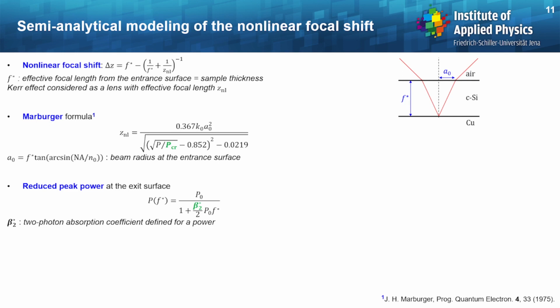And we also modified this formula because for silicon, you have to take into account the losses during the propagation. So we took into account the reduced peak power with this equation here, and this beta 2 star is the two-photon absorption coefficient defined for a power.